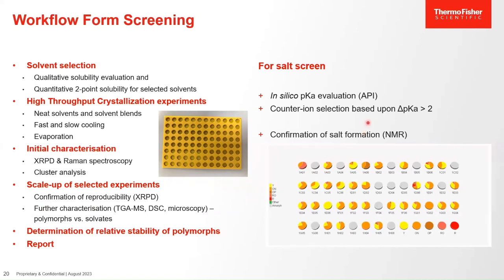There is a subtle difference between polymorph screening and salt screening in that salt screening, first of all, requires a two-component system for crystallization, your API and the counter ion. How do we choose the counter ions? This is done based on pKa values of the API, and we calculate these in silico unless the pKa value is already known.